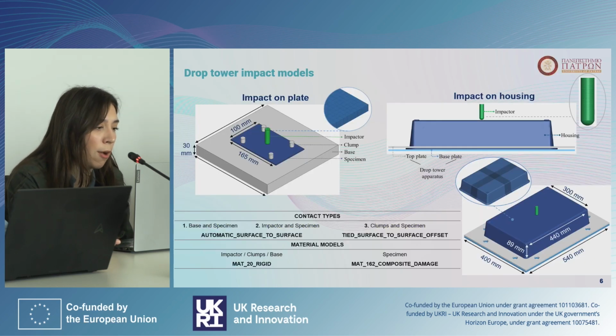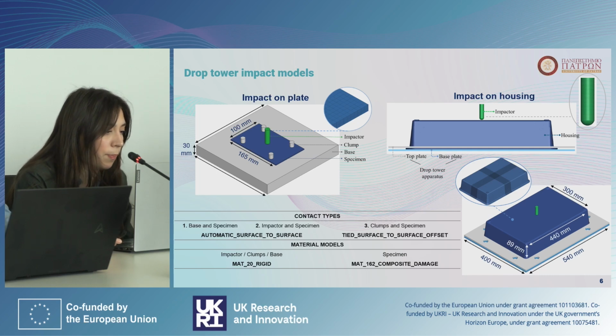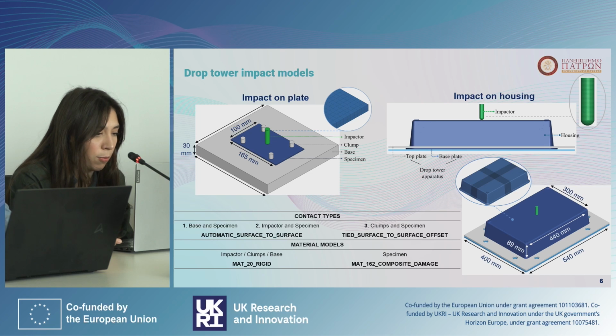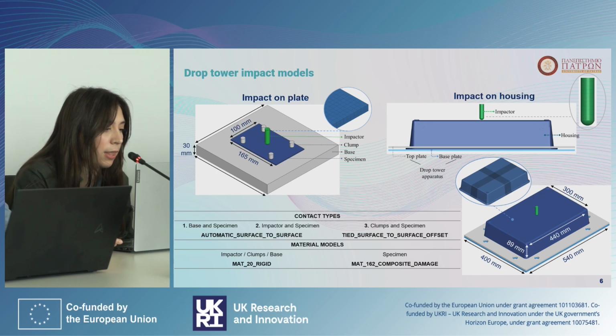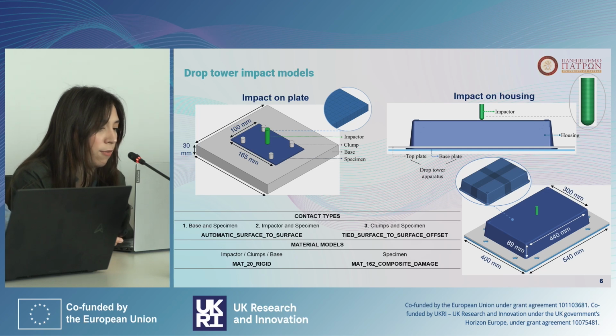The first drop tower model simulates the impact event of the projectile striking the SMC composite, the flat plate, and the setup replicates the configuration of the experimental drop tower apparatus with a steel support base with 4 clamps and a steel impactor. The specimen representing the SMC composite plate was modeled using material model 162 in LS-DYNA, which enables progressive failure analysis of the composite material, incorporating the Hashin failure criteria with the damage mechanics-based softening behavior following damage